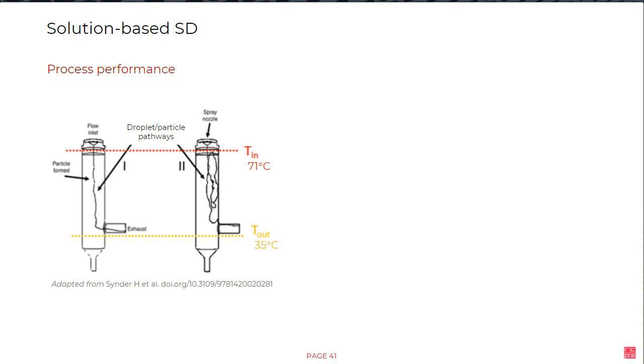This solid particle will just follow this center line very nicely and go directly to the outlet, and then it will be exposed to 35 degrees, which is the outlet temperature. We shouldn't forget here that when the droplet is still existing as a droplet, meaning that the solvent is in evaporation, it will never reach 71 degrees, because the saturation temperature of the mix of the vapor and the gas will be lower than that, let's say around the wet bulb temperature of this mixture. So it will never reach 71. In this case, the particle will only be exposed to the highest 35 degrees.